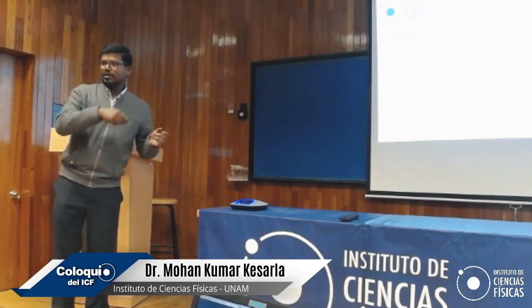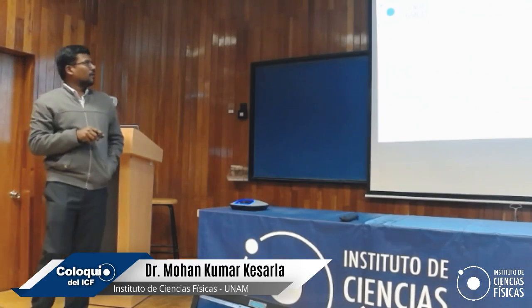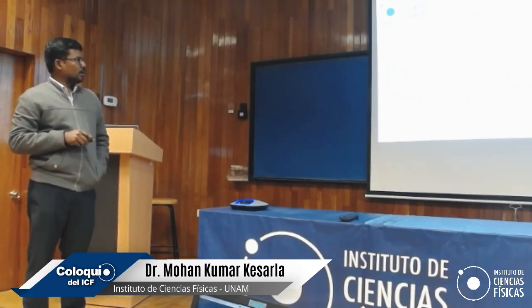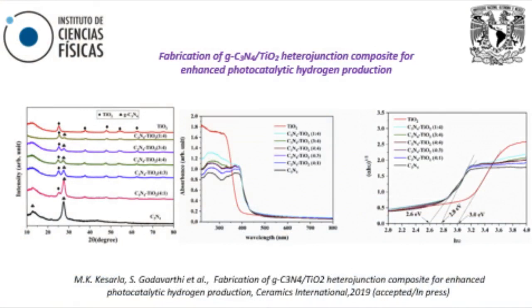So what we did recently, we created a heterojunction with titanium oxide and graphitic carbon nitride, and we varied the content of carbon nitride relative to titanium oxide, and we managed to get an intermediate band gap, not in the UV region, but not as low as g-C3N4. In between, we got 2.8 eV, which is good for visible light photocatalysis, and this is the heterojunction we found. If you can see, this is the g-C3N4, and you can see the formation of titanium oxide on the g-C3N4, and it's a type 2 heterojunction.